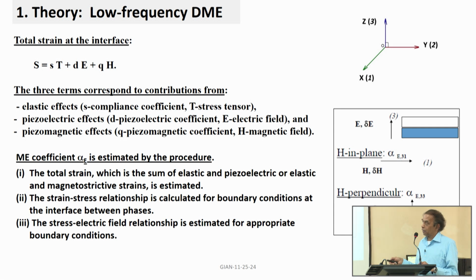So, the way it is done is you estimate the magnetoelectric coefficient with this three-step procedure. The first step is to estimate the total strain at the interface, which is the sum of the elastic strain and, if it is an electric field, the piezoelectric strain; if it is a magnetic field, the magnetostrictive strain. So you find this term S. Then you have to estimate the strain-stress relationship at the boundary between the two phases, and then you can estimate the stress-electric field relationship. The boundary conditions are also important. The bilayer can be free to expand along direction 3, or if you clamp it, the boundary condition will change.